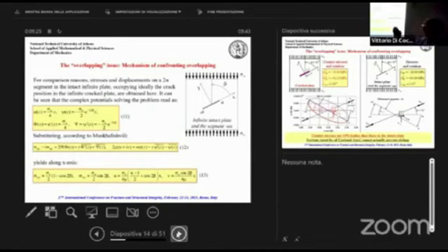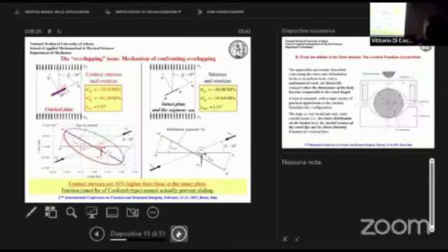Now, just for comparison, we could consider the intact disk with a linear segment equal to the crack and crack disk. And now we can calculate the contact stresses, which in the problem of the infinite medium are constant all over the crack. You can see that the contact stresses are relatively close to the stresses that are developed in the linear segment of the uncracked. And the same is true for the rotation. We have a rotation of about 2 degrees in the cracked plate. We have a rotation of about 1.3 degrees in the intact plane.